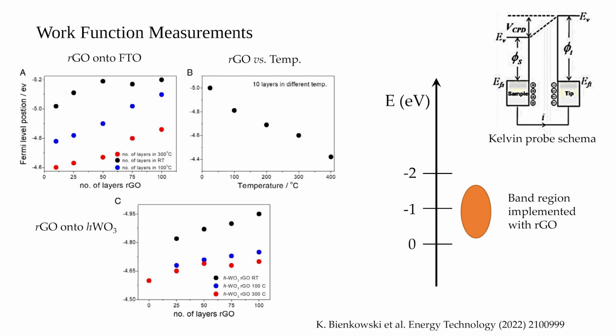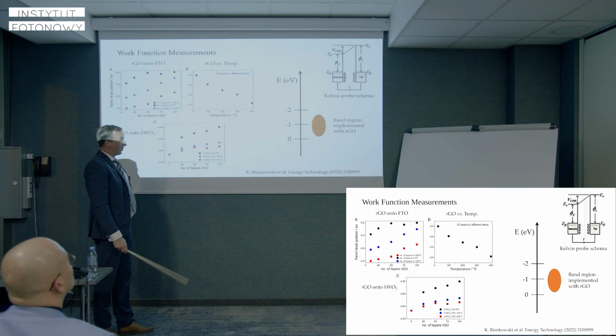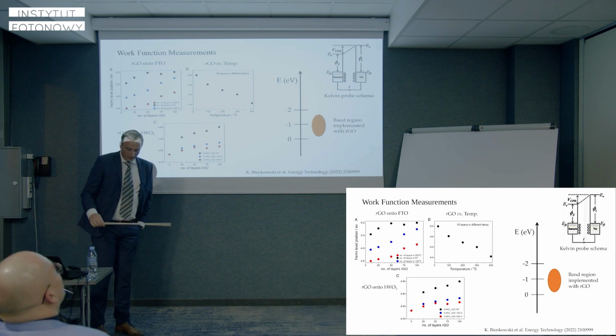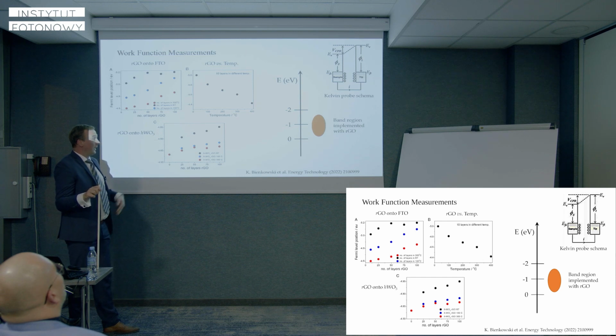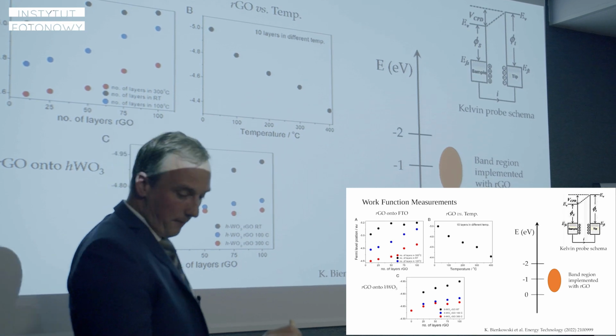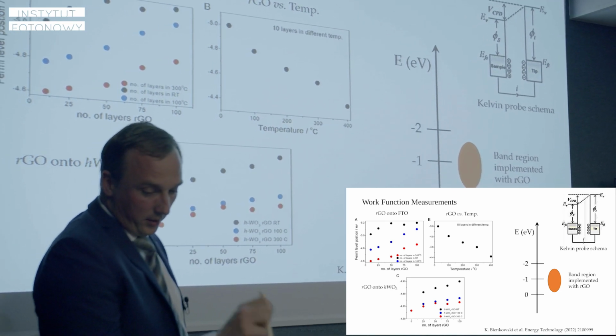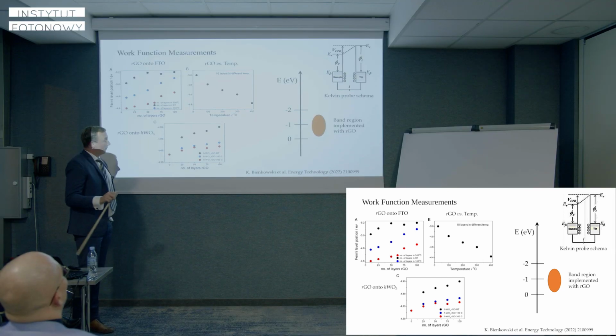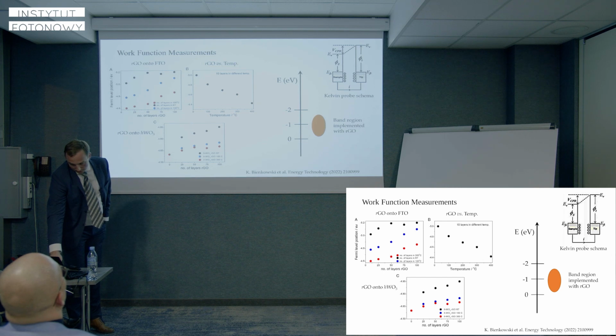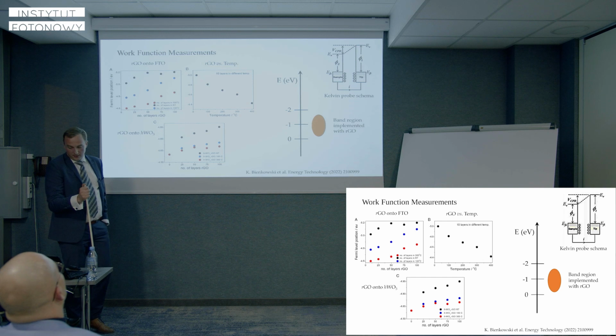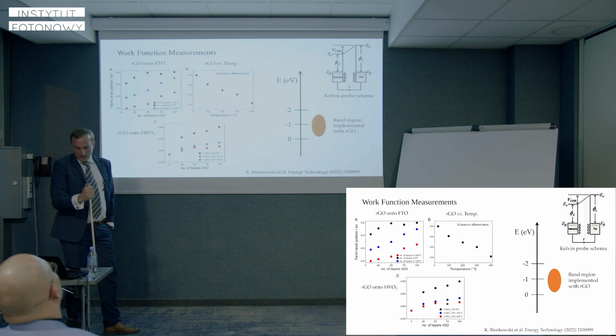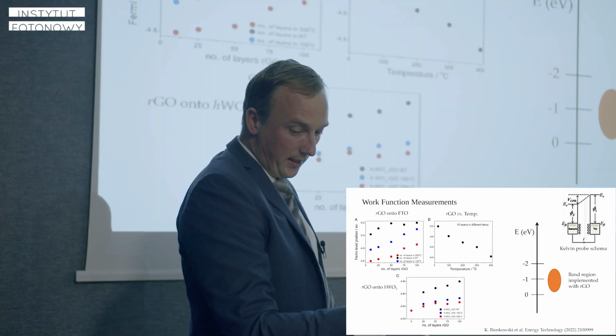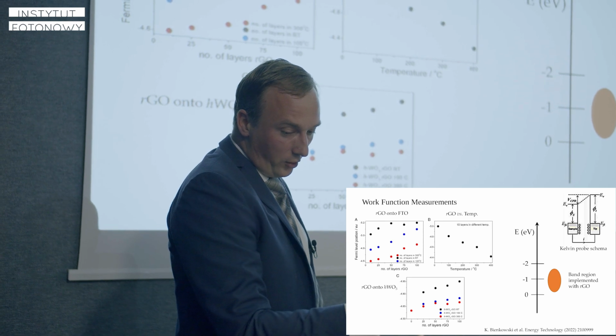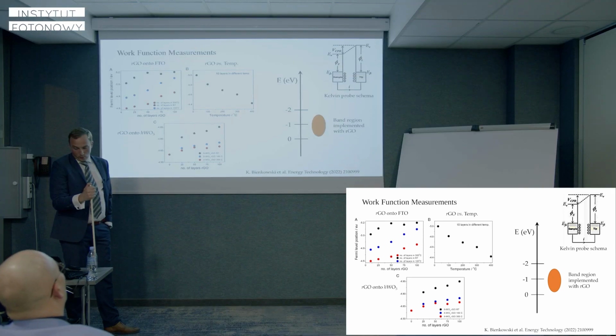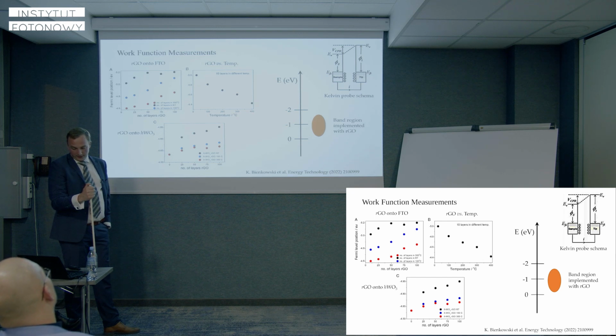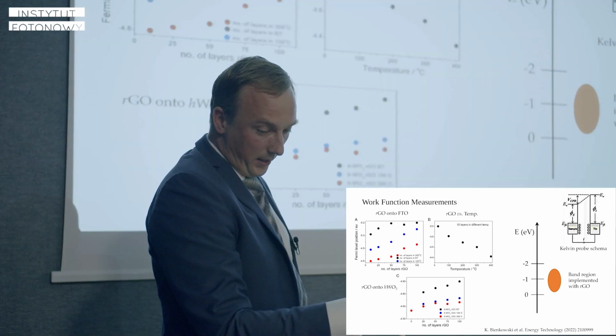We measured the work function of our system, our modification with reduced graphene oxide, and we also heated our materials at different temperatures. Our reduced graphene oxide was deposited on FTO, a conductive glass support. Manipulating the number of RGO layers directly affects the Fermi level position, mainly because it induces charge transfer between the substrate and RGO. The charges are subsequently distributed through the layer. However, the electrode thickness affects other key properties of the material, such as thermal and electrical conductivity and transparency.